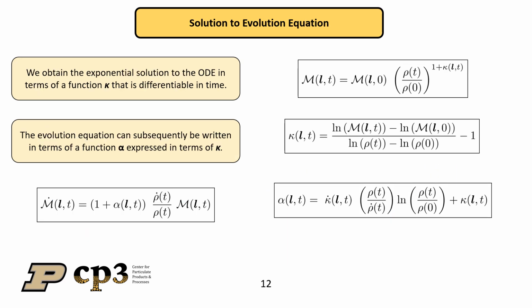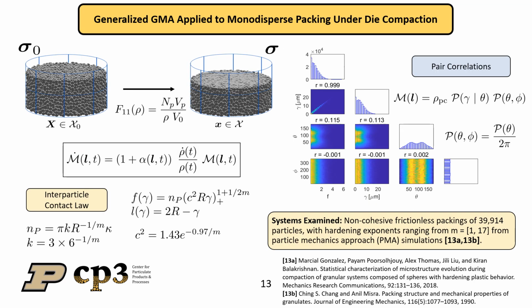We now propose a possible solution to the evolution equation that takes the form of an exponential function in terms of a function kappa that is differentiable in time. We now apply this approach to the case of a monodisperse packing under die compaction. We specifically examine non-cohesive frictionless packings of approximately 40,000 particles with varying hardening exponents from results from particle mechanics calculations.